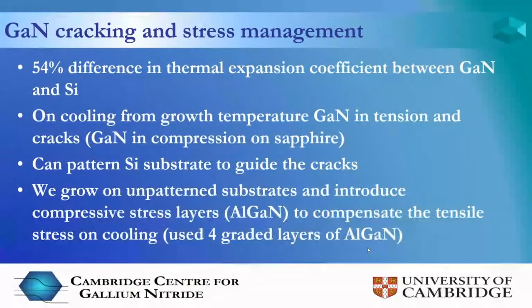So, another problem to solve. Okay, so that problem was solved by using this buffer layer. Another problem to solve is this huge difference in the thermal expansion coefficient between the two materials when you cool down from the growth temperature of 1,000 degrees centigrade, which puts the gallium nitride in tension. And so what we did then was we deliberately introduced into the gallium nitride, as we were growing it, another material, which was aluminium gallium nitride, and that actually puts the material under compressive stress. So we balance the tensile stress on the gallium nitride from the silicon with the compressive stress of this aluminium gallium nitride layer. So this is really straight engineering at the atomic level.